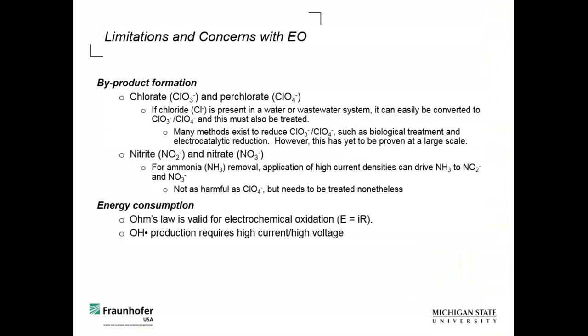Okay, so limitations and concerns. So this blessing and a curse thing. When we have chloride in solution, depending on the current density, usually people say you need hydroxyl radicals to do this, but we make perchlorate. So that's one, and that's actually a specific Achilles heel of diamond in this method.